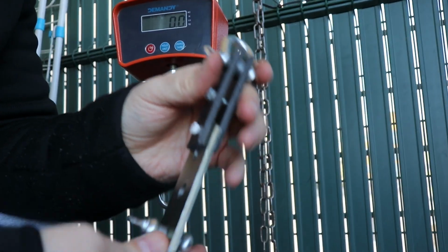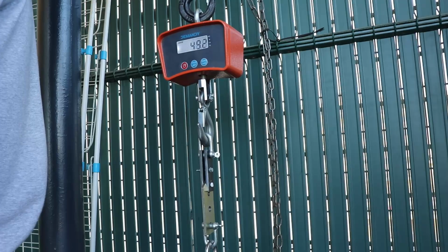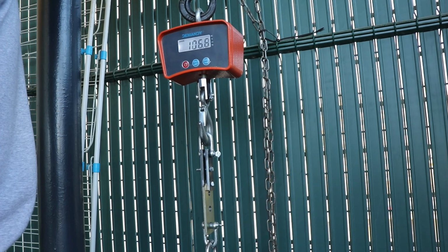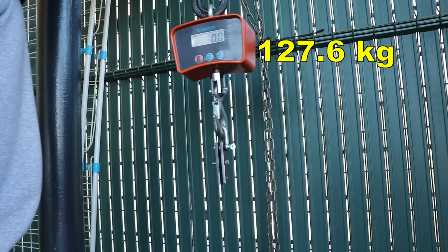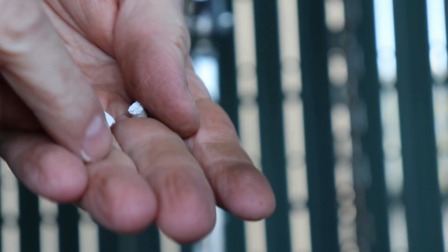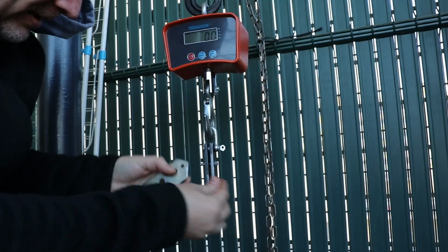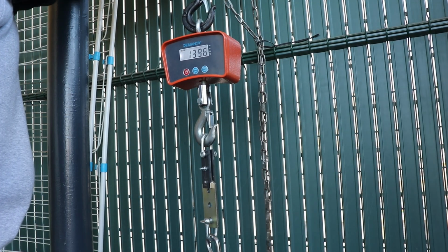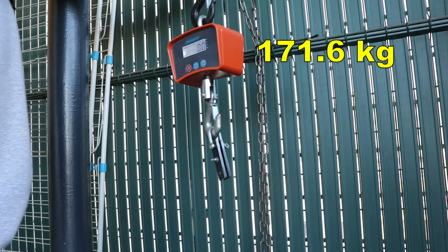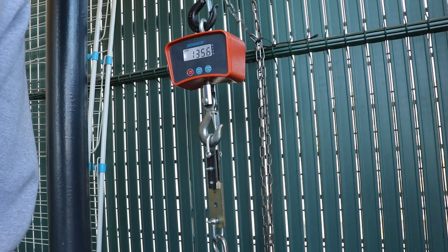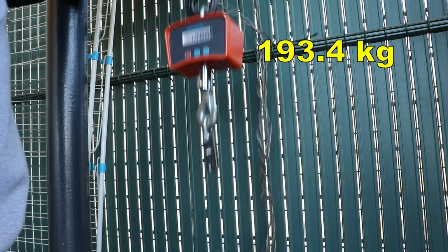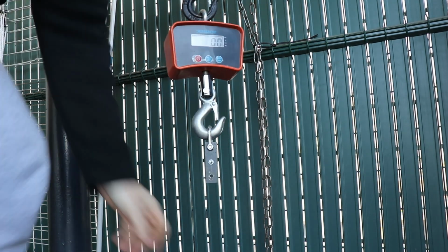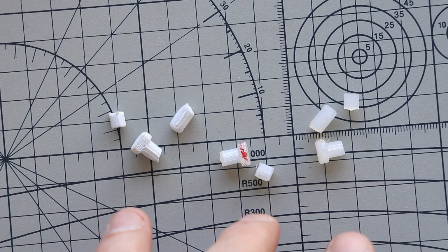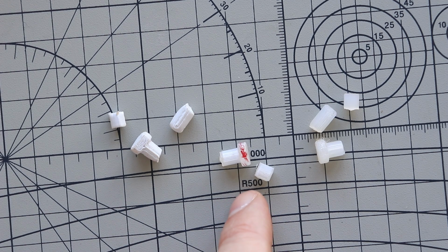And the next mechanical test is the shear stress. The diameter of these test specimens is 5 mm, but the area is doubled, and I'm starting with ABS. And it broke into exactly 3 parts. And the next one is polycarbonate. It just exploded, but it also broke into 3 equal pieces, only I couldn't find one. And then the nylon. And this was really strong. ABS, polycarbonate and nylon, and they broke exactly how they should, on those 2 cross-section areas. They are sheared. And here I missed one piece because I couldn't find it.